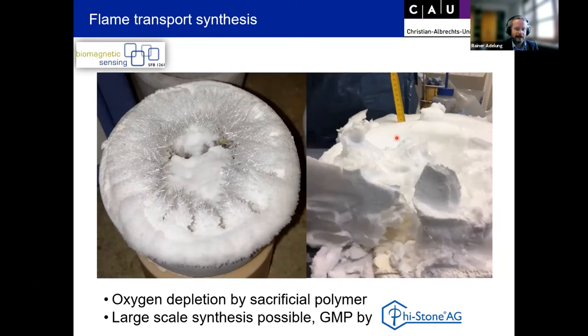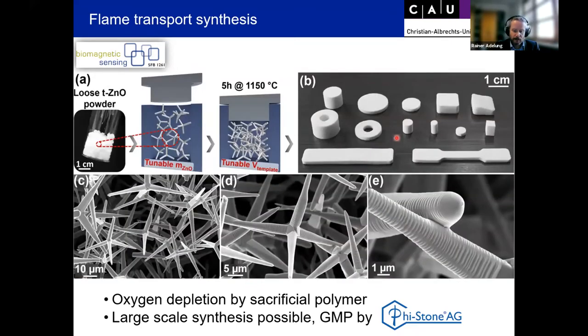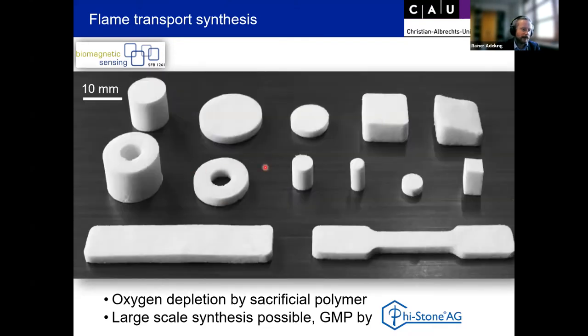You can see here a ruler sticking in this material — it's really mass-produced. In order to give a more distinct shape and control the properties, you can take this tetrapodal powder, which is loosely held together, compress it a little bit, and make templates for sintering it in various shapes. After sintering, tetrapod arms are sintered together as interconnects. In this way you can have ring shapes, rods for tensile tests, and so on — you're very flexible in dealing with this material.